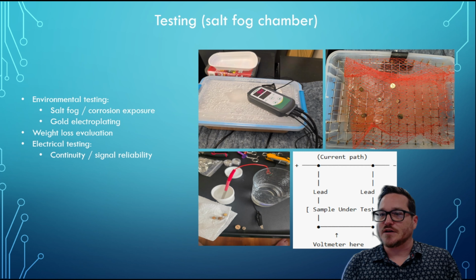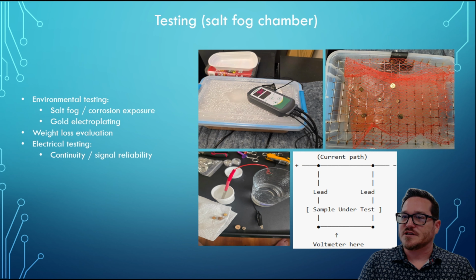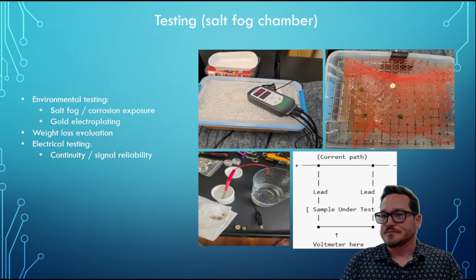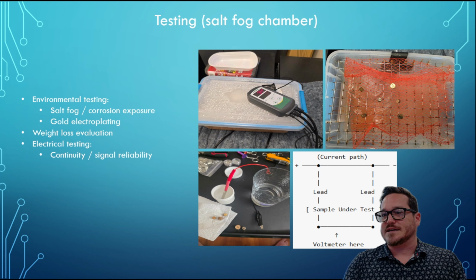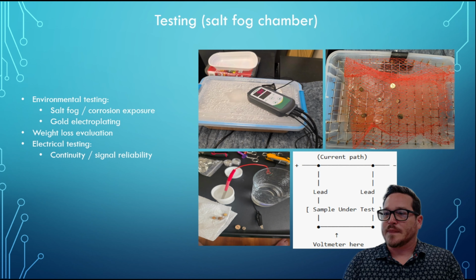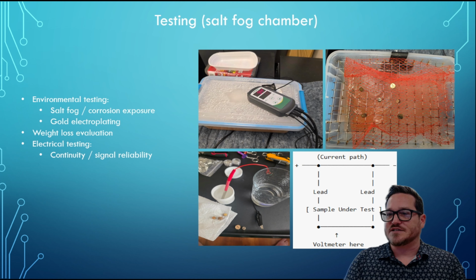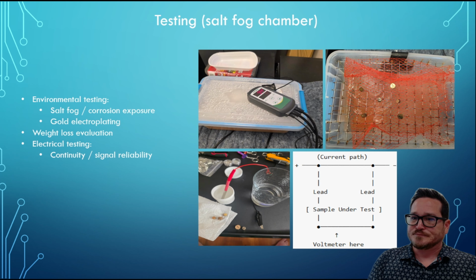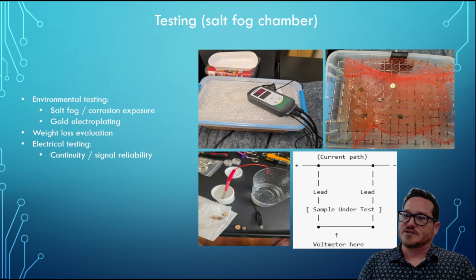To further test the metal used for the new contact pins, I built a salt fog chamber. This chamber is a sealable plastic container. Inside is a saltwater solution, an ultrasonic fogger, and a wire frame with plastic mesh to hold the specimens. Under the container are 2 silicone heating pads that are plugged into a temperature controller. The temperature controller uses a probe installed through the top of the container to detect temperature.